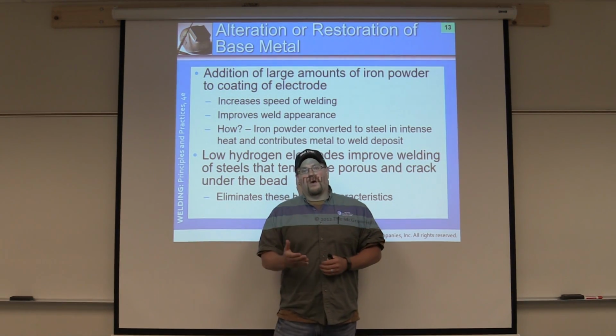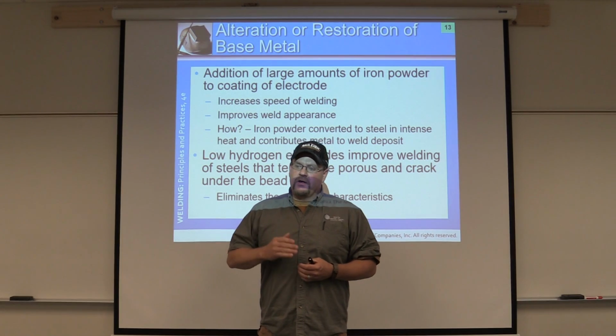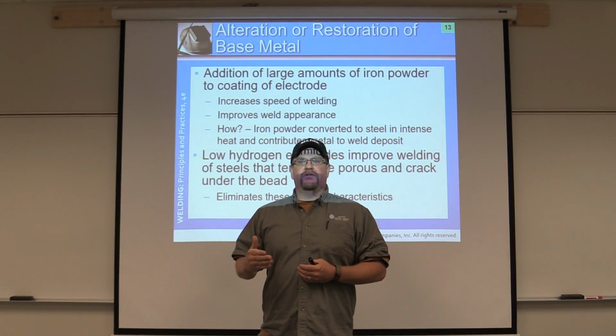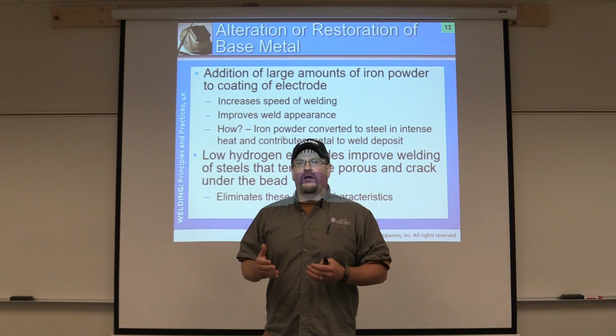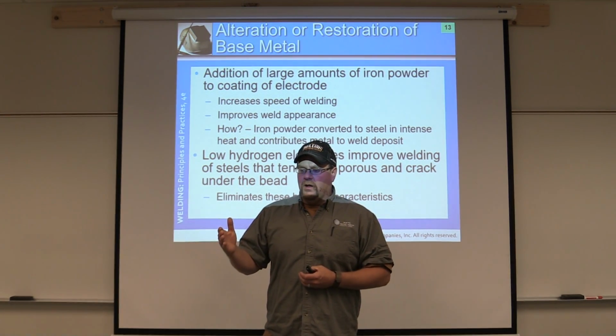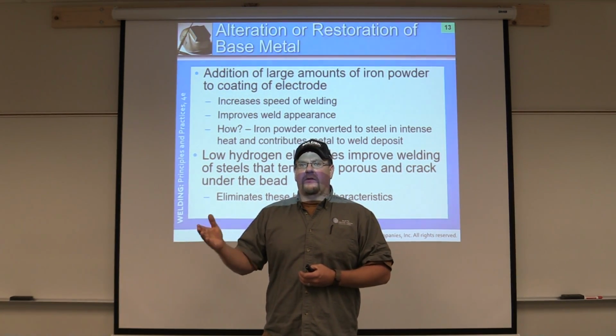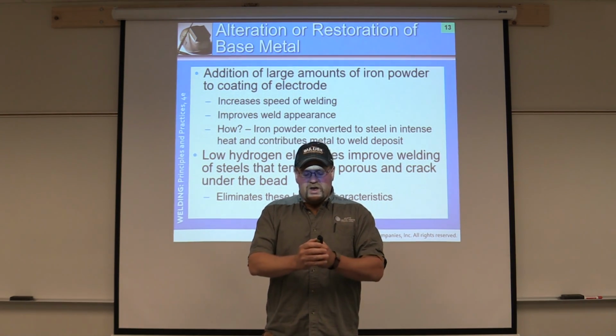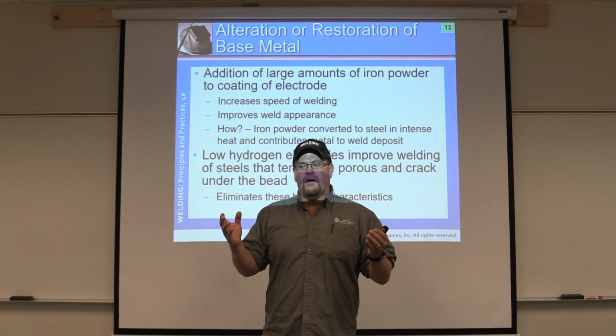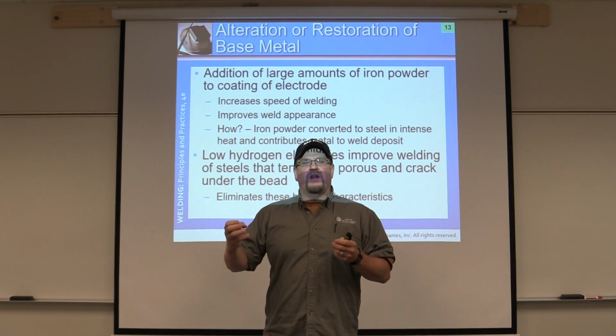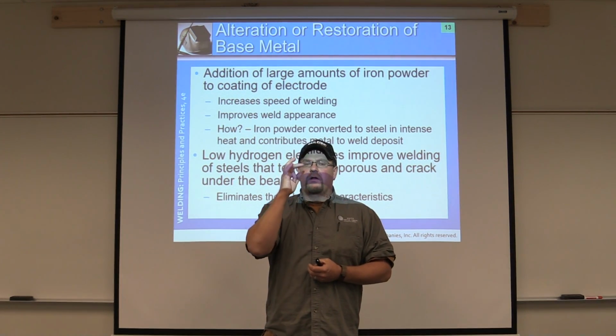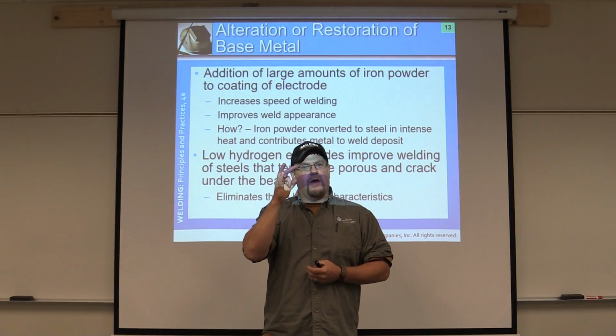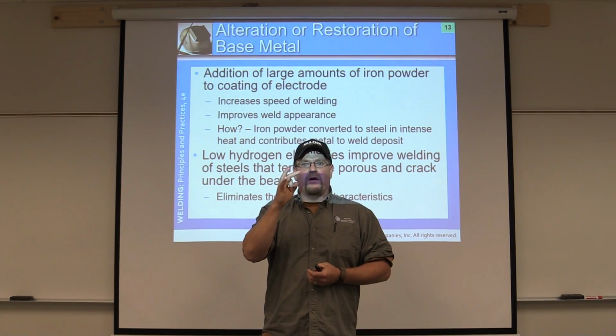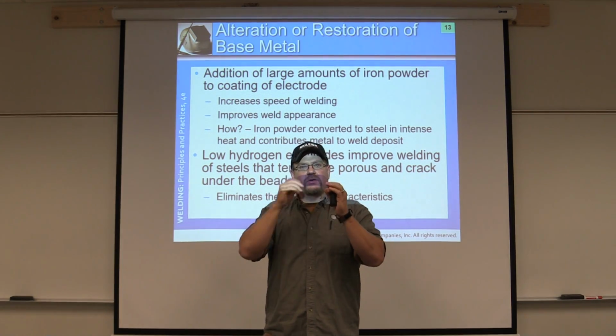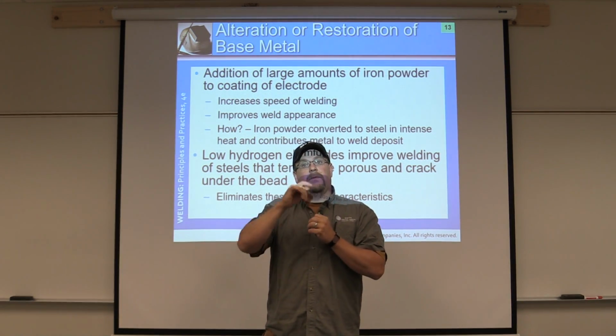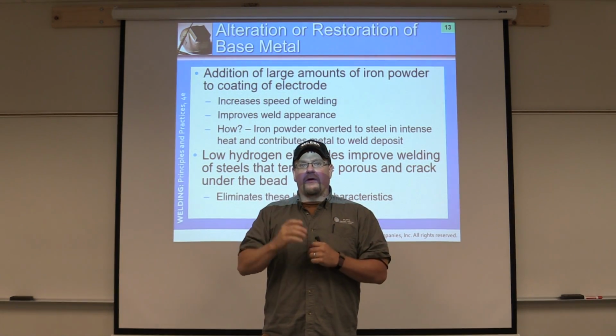So at that point, the way that code regulation sees it, most shops will say, take the 7018, it's a low hydrogen rod, it's designed to be a low hydrogen rod. You need to put it in a rod oven, bake it up to 250, 350 degrees, and let it sit there. And what that does is it dries the moisture out of it, okay? So that way there's no moisture within it that's going to get pulled into the weld pool and create little spots of porosity, aka hydrogen, inside of the weld pattern. And if we get enough of those lined up, it's kind of like Swiss cheese or holes in a bridge. What's going to happen is the dots are going to connect and we're going to have a weld failure, okay?